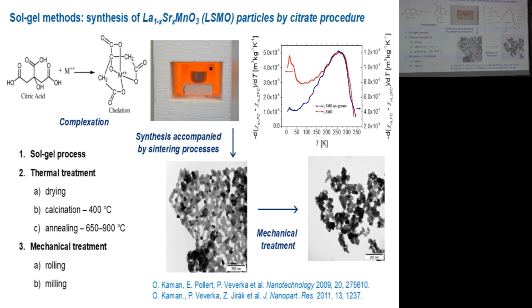So, for example, one procedure that belongs to this group is the citrate procedure, where you use citric acid that forms some complexes with metal cations. There can be different coordination modes of these citrate anions, but you can imagine some complexation of the metals in solution. But you will add also ethylene glycol, which will, during heating, react with some free carboxylic acids of the citric acid, and there will be esterification. So it will polymerize through forming esters, and also there might be even formation of ether bonds during the reaction of the hydroxylic group of the citric acid and hydroxylic groups of the ethylene glycol. So this is the way how chemically the gel is formed.